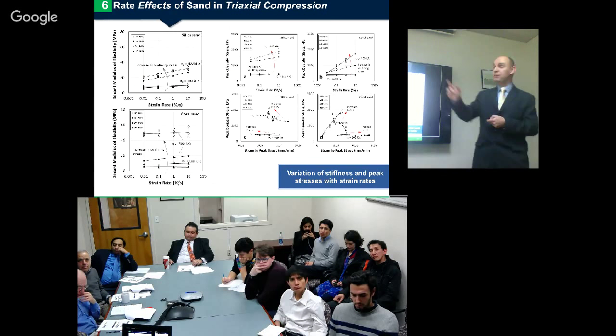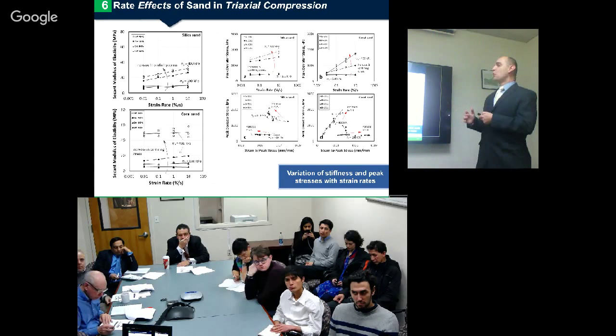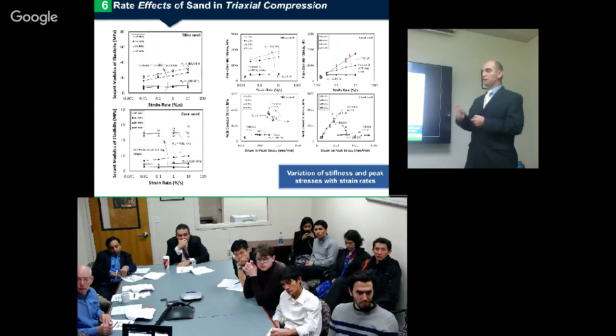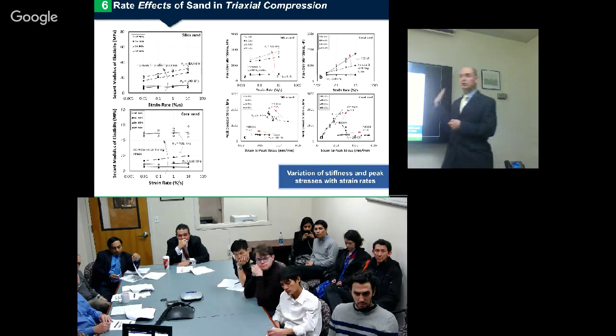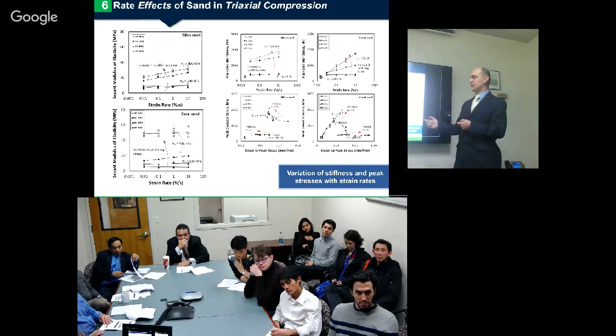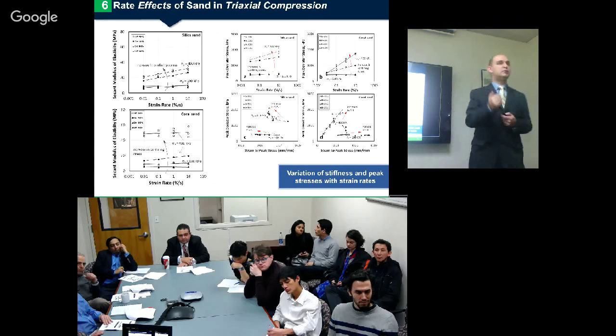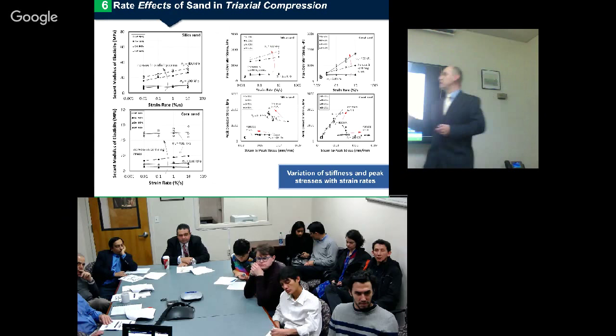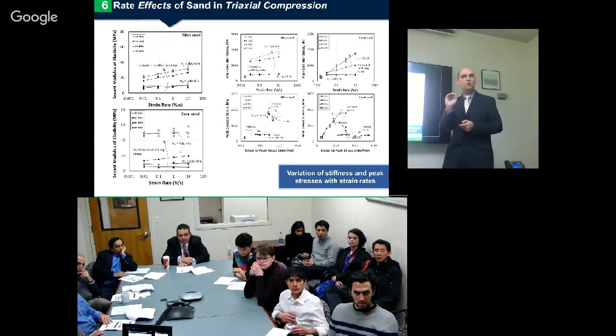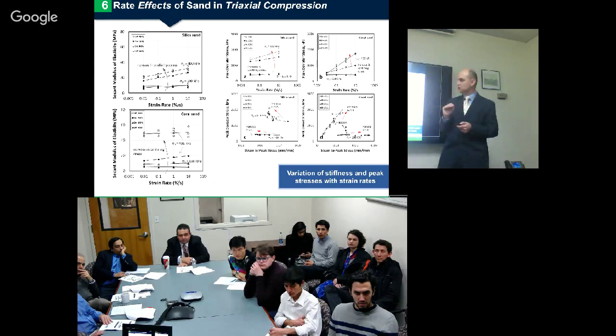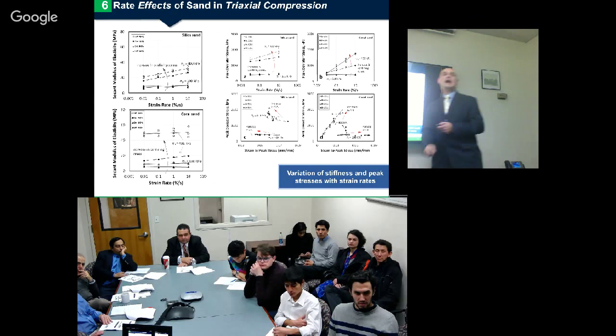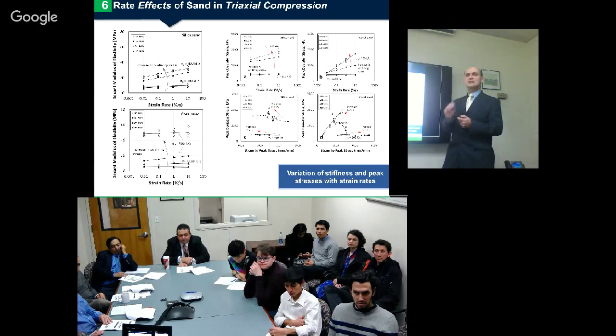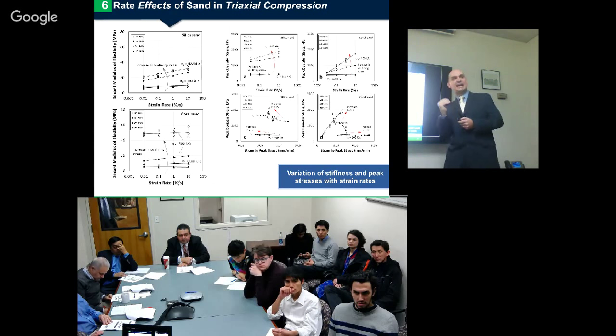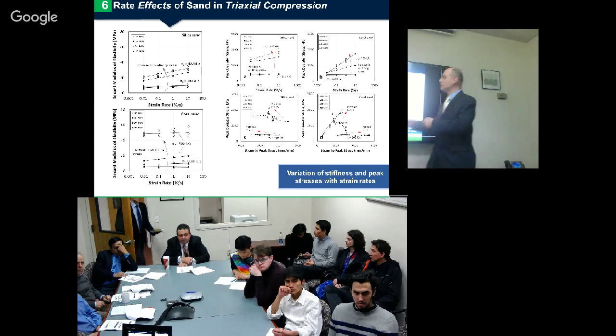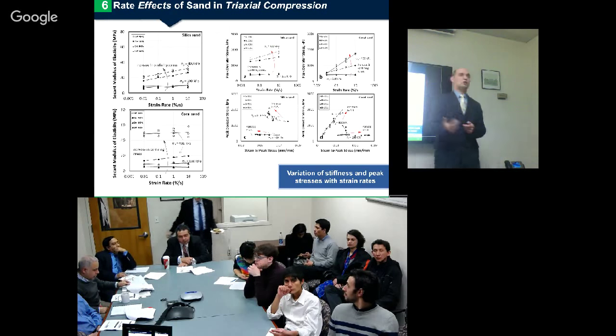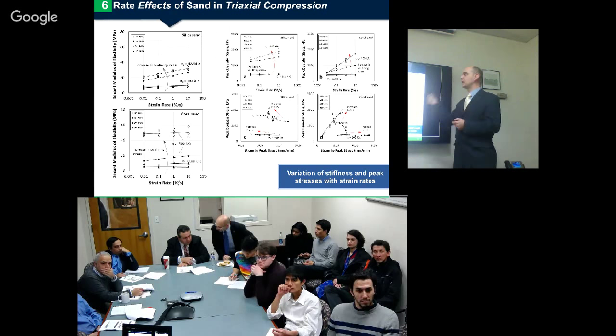Now, based on these previous tests, I thought of the variation of the secant modulus of elasticity versus the strain rate in these two materials, on the left side of the screen. Silica sand on top, coral sand at the bottom, to see how the strain rate is affecting the stiffness of the material. We can see that at very low confinement stress, the line is typically horizontal. We can also see that in coral sand when we have a high 100 kPa confinement, we see a slight, greater effect on the stiffness of the material that we can identify somewhere here. So in other words, the confining stress is important under these conditions.